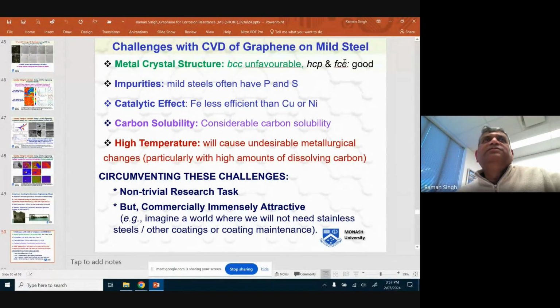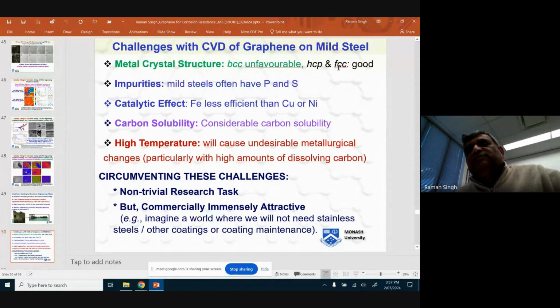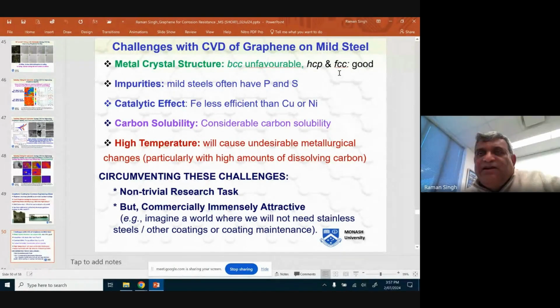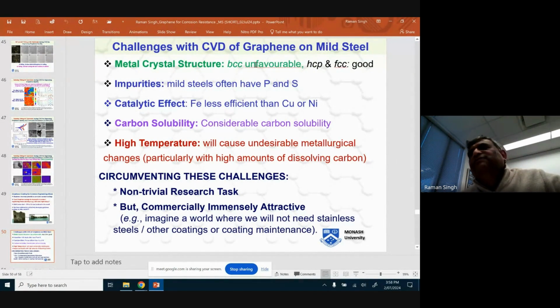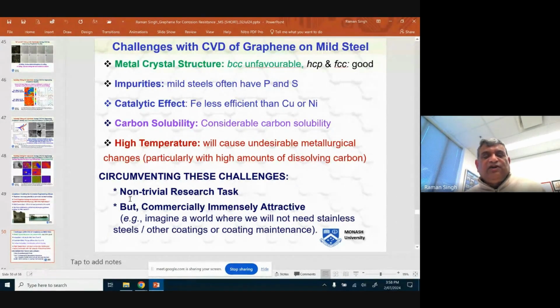Fine, that's good. When we cool down, there will be a phase transformation from FCC to BCC. And remember, I said BCC has 100 times less carbon solubility. So all of a sudden, a lot of carbon will be rejected from the steel or iron, and the carbon supply to the surface will be so excessive that developing graphene will not be possible. So this is a prohibitive scientific challenge because of which one cannot develop graphene on mild steel by CVD. I'm talking about pristine graphene. That's the main trouble. So it is a non-trivial task.